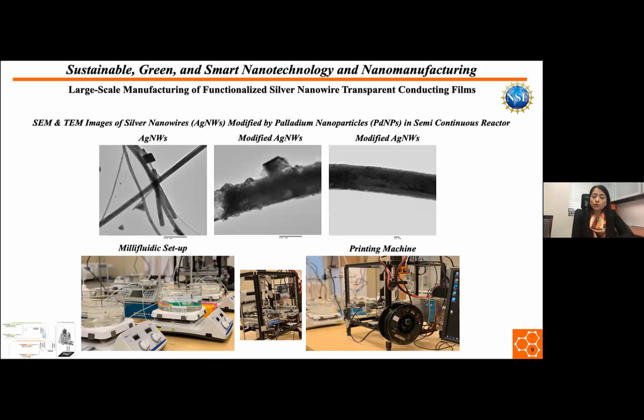But our ultimate goal is to have continuous synthesis of silver nanowires and continuous modification of silver nanowires using palladium nanoparticles. And here you can see the millifluidic setup that we have in our lab in order to do that. We haven't used it yet, but we are going to use this system to produce silver nanowires continuously, have them modified using palladium nanoparticles at optimized reaction conditions, and then finally we can send the modified silver nanowires to the printing machine, which was developed and designed by Dr.